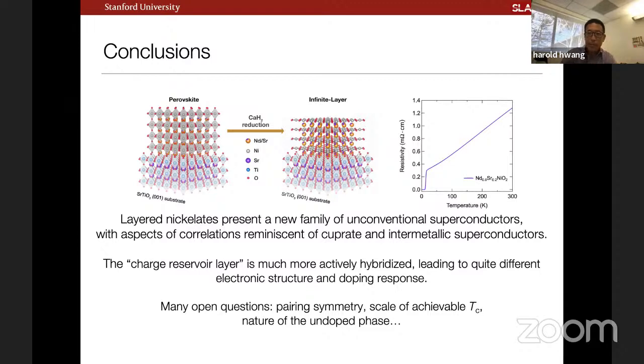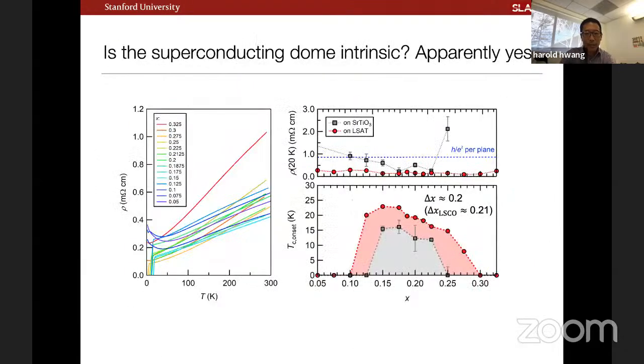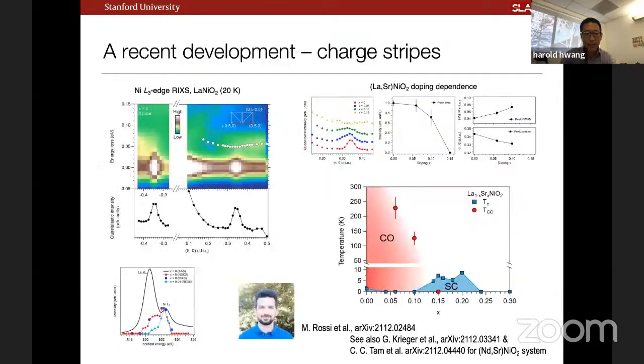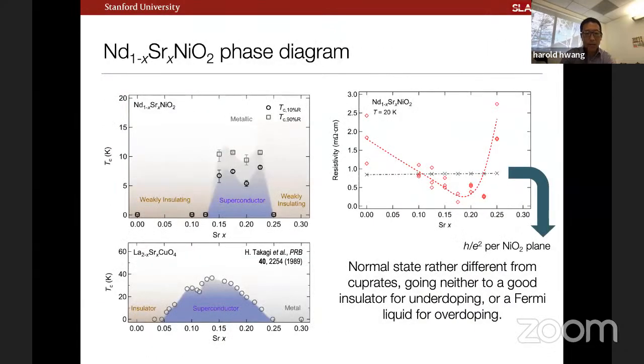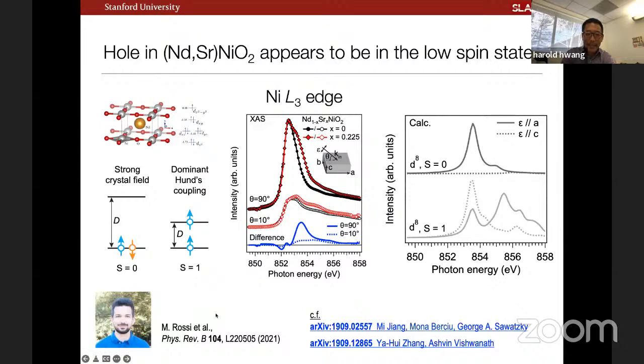Yeah. So indeed, this question has been lively in the nickelate problem as well. I had showed some work from Ashvin's group, and I think Mona and George at UBC. There's also been work from Kotliar's group worrying about this. And so indeed, it looks, at least theoretically, very close in energy. All I can say is that in terms of directly looking at this problem, we probably haven't looked extensively enough. But in terms of XAS, it looks like it's quite dominated by the low spin state configuration.